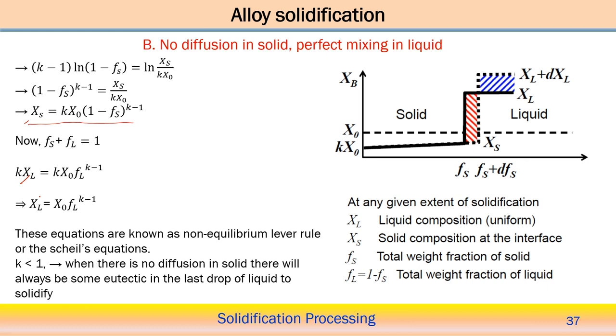Therefore this equation is basically the non-equilibrium Lever rule, and we can utilize this equation to understand the solid fraction and liquid fraction. In this particular case of solidification, we are assuming there is no diffusion in the solid phase, but there is perfect mixing in the liquid phase. In that situation this equation is applicable. But remember, when there is equilibrium solidification, we can utilize the Lever rule, because with the Lever rule we can estimate in a proportionate way the solid fraction and liquid fraction during solidification. But in this case we cannot use that; this is also called the non-equilibrium Lever rule. Here it is not linearly related to the other parameter; it is non-linearly related.